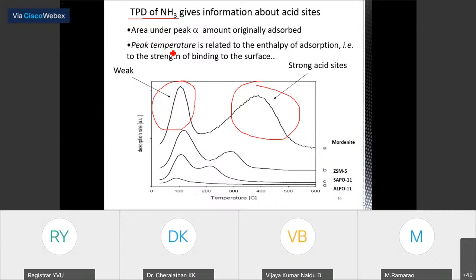Initially, ammonia is adsorbed on the material, and then it is desorbed by increasing the temperature. On the x-axis, I have temperature, and on the y-axis the desorption rate. Based on the temperature at which this desorption takes place, we can tell whether the material has strong acid sites or weak acid sites. The higher the temperature of this desorption, the stronger the acid site. That is the idea. And not only that, we can also quantify the acid sites. The area below these peaks gives you an idea of the amount of acid sites present in the material. So temperature programmed desorption of ammonia is used for this purpose.